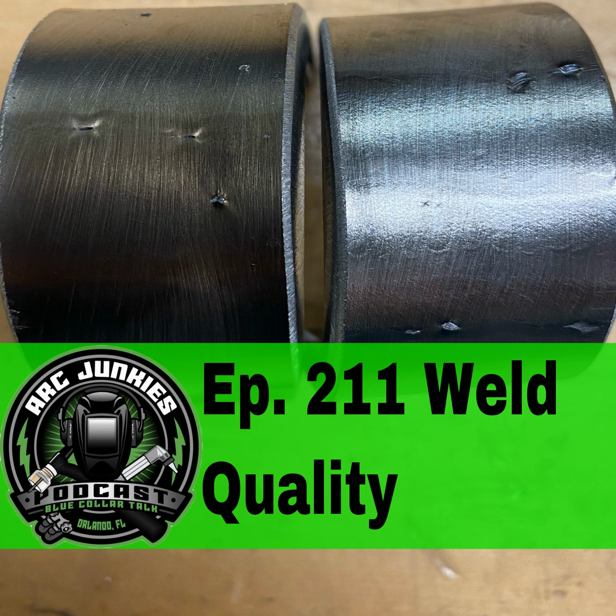All right, so up next is excessive reinforcement, and that is the excessive amount of groove weld which extends beyond the surface of the plate, caused by too slow of a travel speed. Well, typically caused by too slow of a travel speed. But anything, like I do a lot of work to D1.1, so anything greater than an 1/8 inch of weld reinforcement is considered excessive weld reinforcement, and we have to reject the plate at that point.